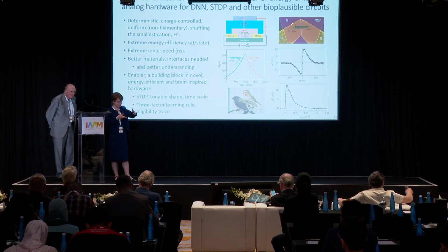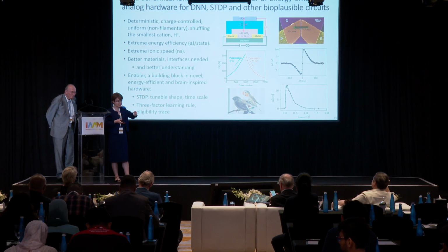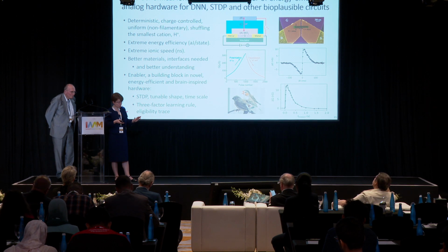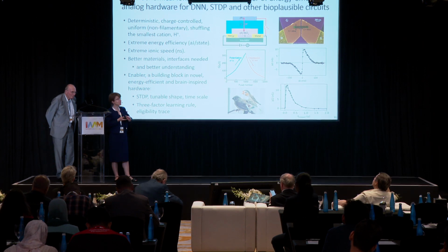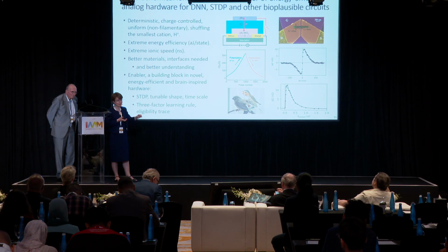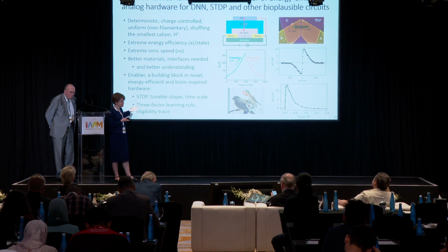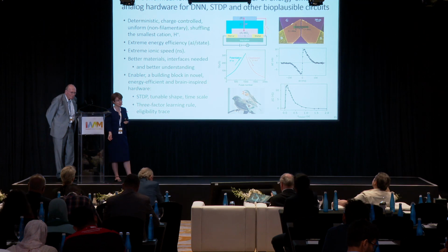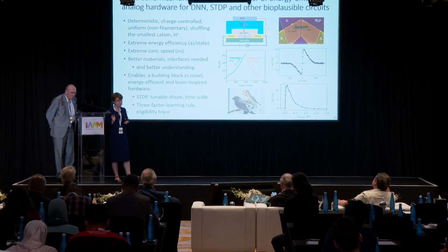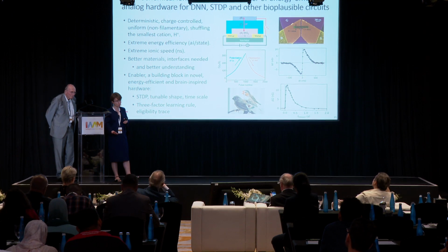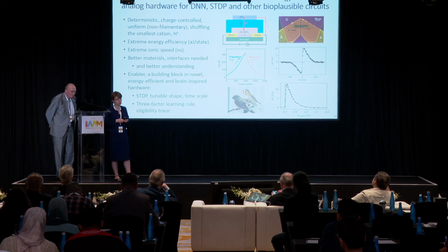For a 10 nanometer by 10 nanometer device, you need to be in the nanosiemens regime. So the high resistance should be really high. And then you modulate within about 10-fold of it at the least. So there is a cap on how high conductance you can go. And that is at least determined for the hardware DNN context. For SNN or for these other devices, I expect you still need very low resistance, but I cannot quote a number for them. And again, for hardware DNN, we do achieve that very low resistance to start with and modulate within an order of magnitude out of that.